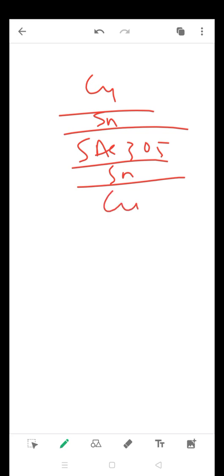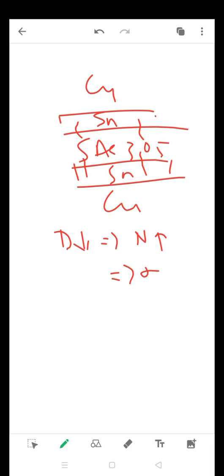So what it is preventing is any major diffusion or any major formation of intermetallic scallops. Okay, so this extra thin layer acts as a diffusion barrier. So that is why the crystallite size is reduced, which causes an increase in the dislocation density, and which actually causes an increase in the conductivity of the material.